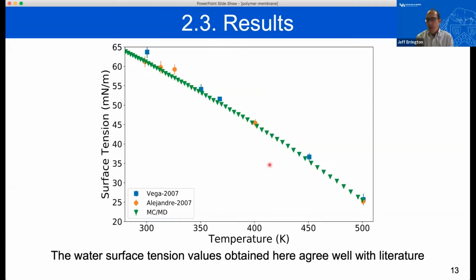As I mentioned before, one of the other outputs that you can get from this type of approach, if you use both a spreading approach and a drying approach, is information about the liquid vapor surface tension, in this case, the liquid vapor surface tension of water. So here we're using an SPC/E model for water, and we're able now to compare the results that we're getting to other literature results. You can see that there's good agreement with literature results, and that provides just a bit of confidence that we're doing these calculations correctly, and we're getting results that are consistent with previous studies for those properties where we can make a meaningful comparison.